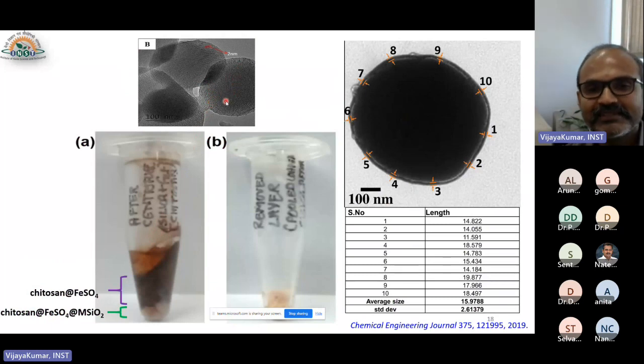Most of the silica loading that has been shown before we have attempted is all with this liquid formulation. They give the saturated solution and they allow the tunnels to be filled. Here, what we have done is we took the saturated solution of FeSO4 and then we applied low pressure with a little bit of heating so that the solvent, that is basically the water, evaporates. During evaporation, the filled-in gaps get diffused in by the salt that is crystallizing, that gets loaded inside.